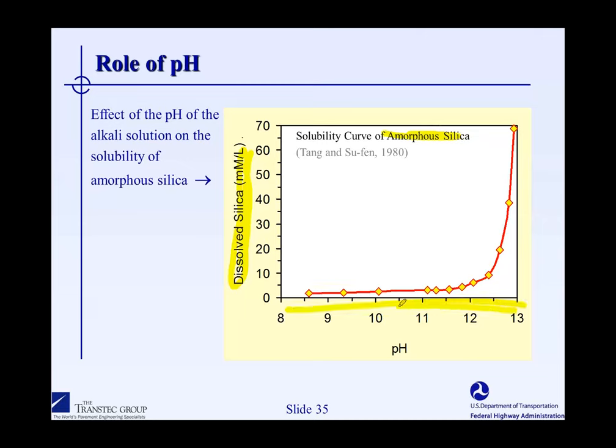a function of pH. And what we can see here, even up to relatively high pHs of 12 and maybe even 12.5, which is the pH of saturated calcium hydroxide solution, virtually no silica passes into solution at all. It's not until we get into the much higher pHs that we start to see silica dissolve. And of course, these are the pHs that we might encounter in concrete.